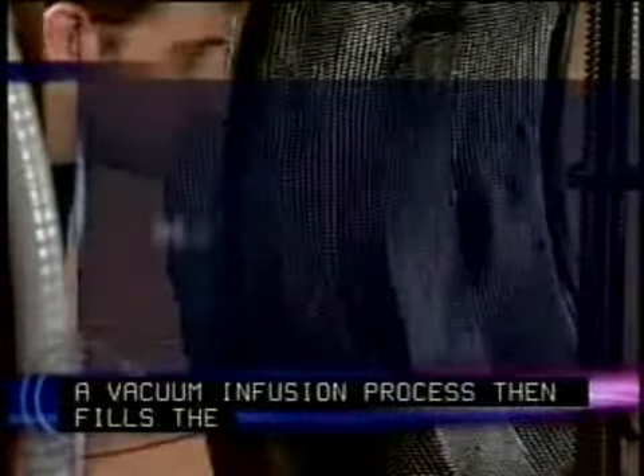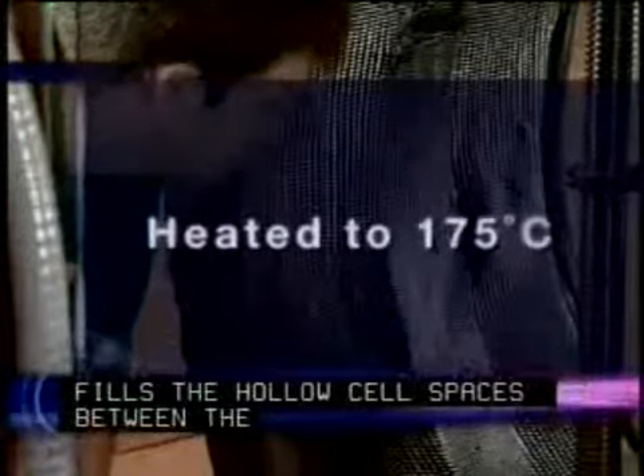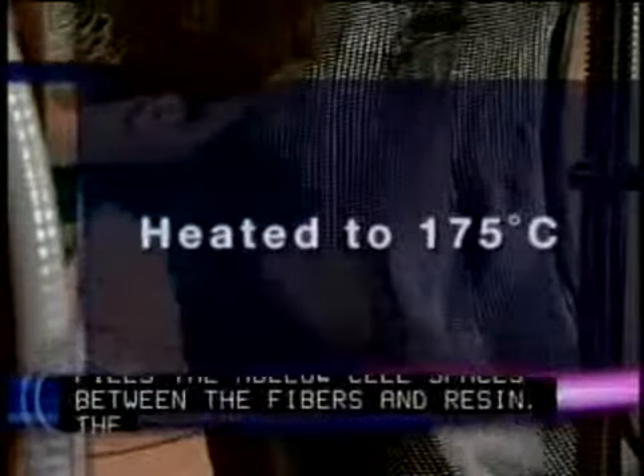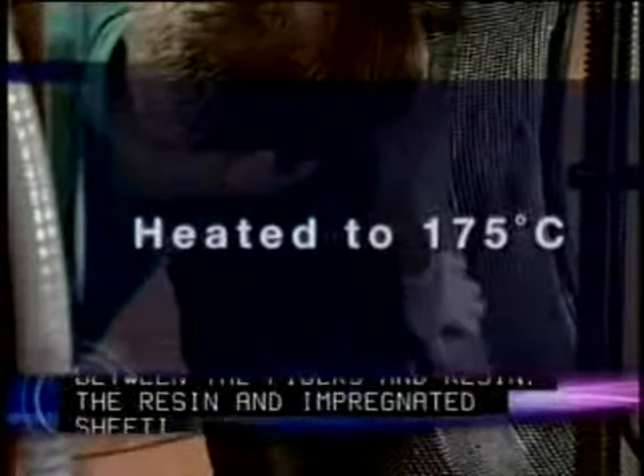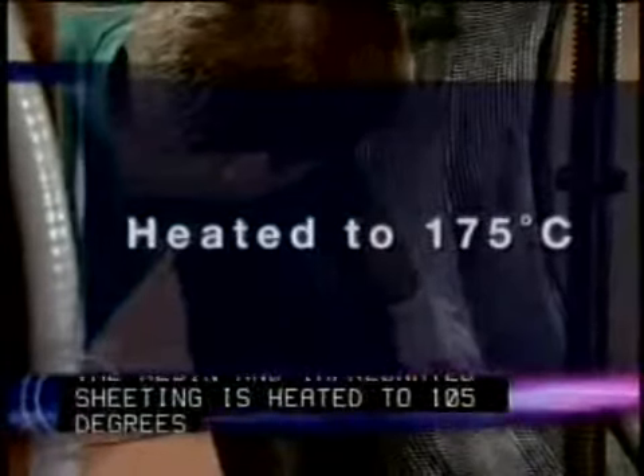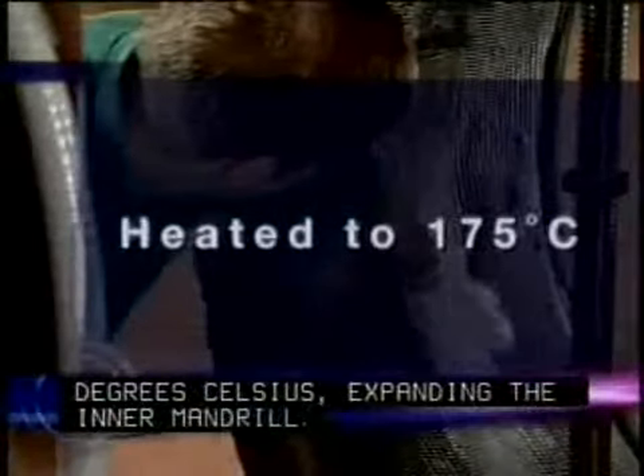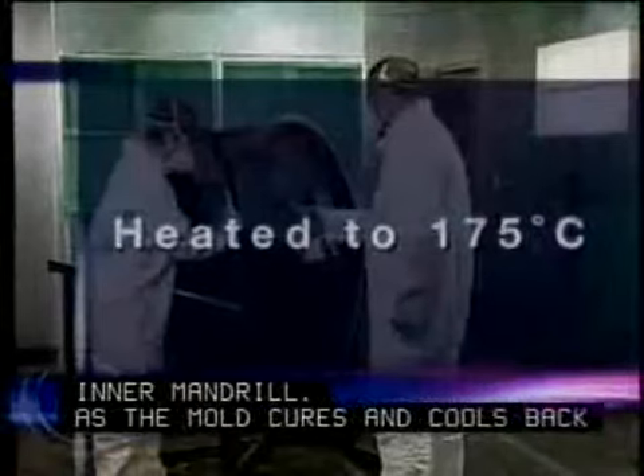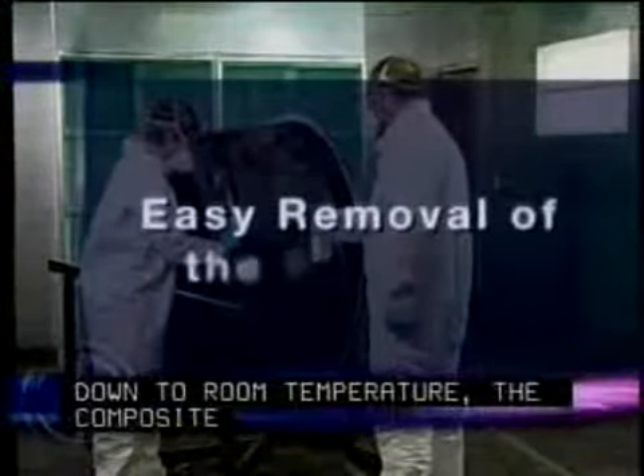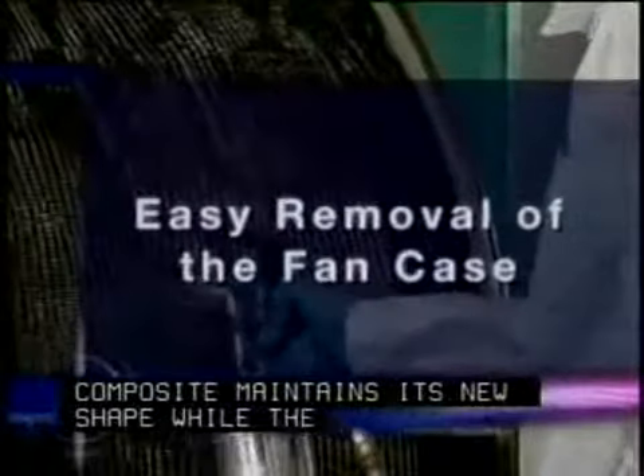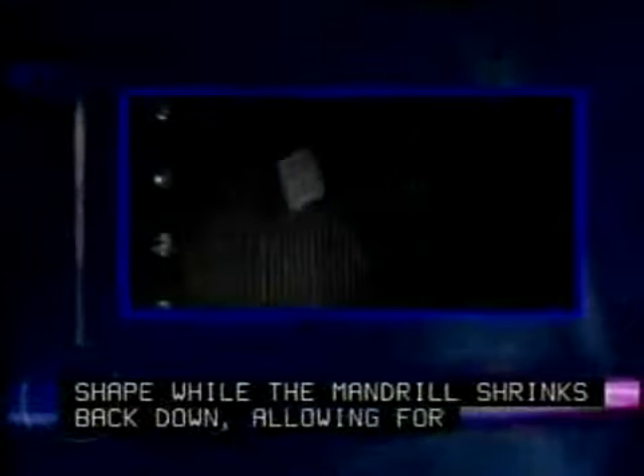The resin-impregnated sheeting is heated to 175 degrees Celsius, expanding the inner metal mandrel. As the mold cures and cools back down to room temperature, the composite maintains its new shape, while the mandrel shrinks back down, allowing for the easy removal of the fan case component from the tool.